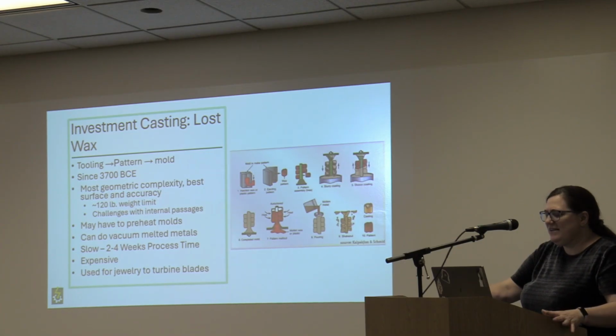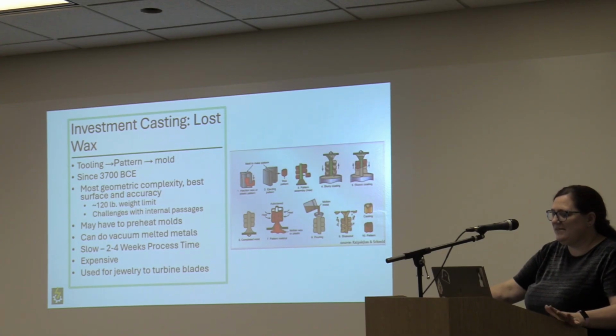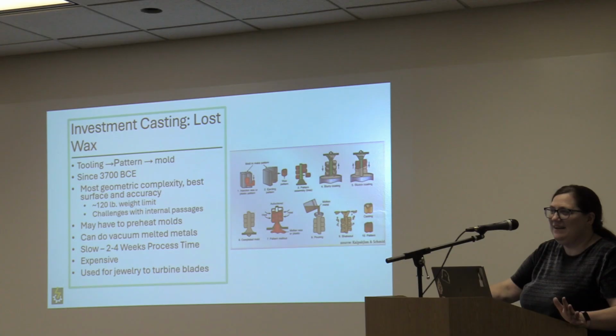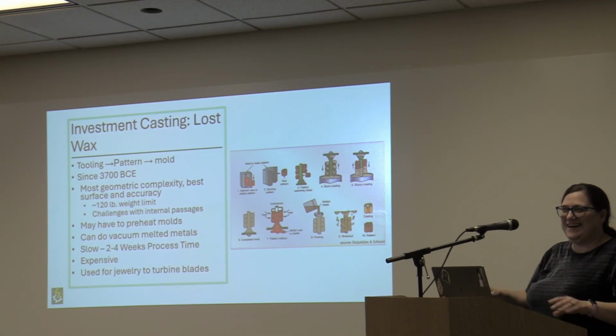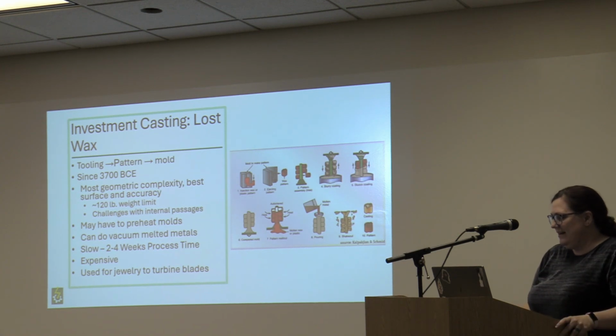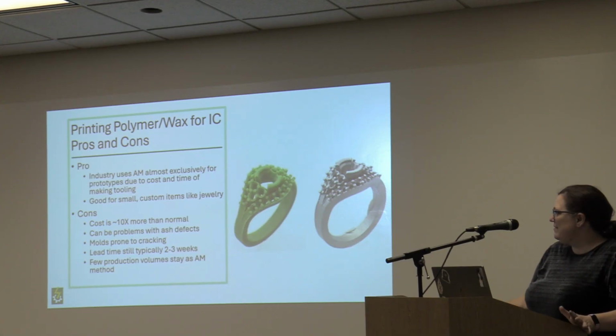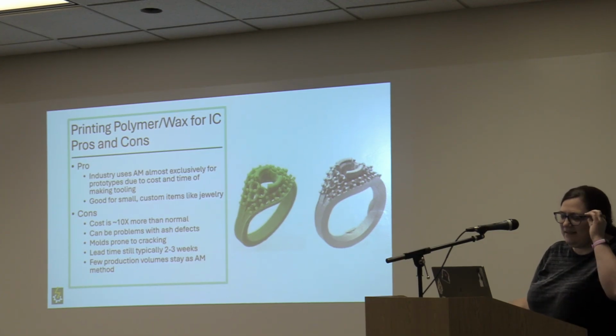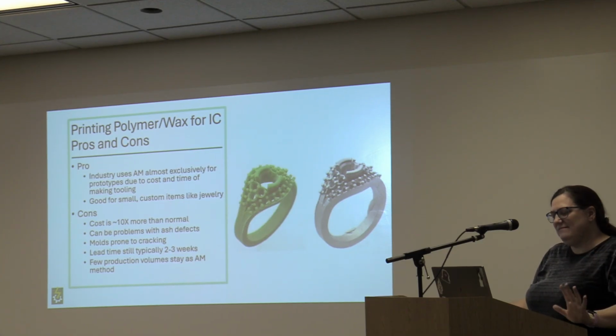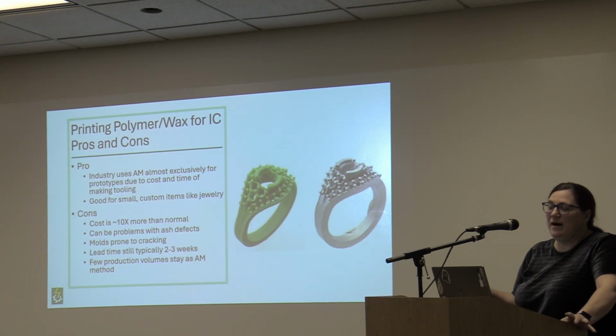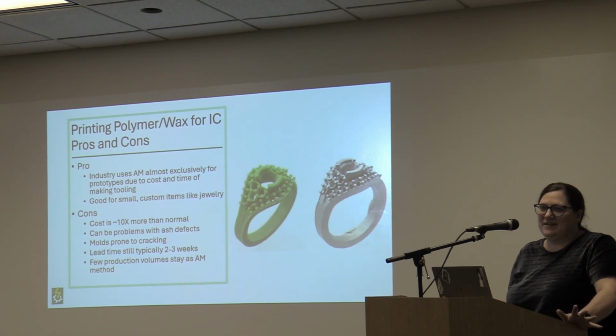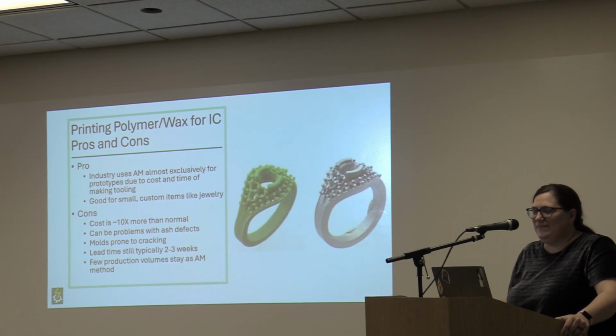And the biggest drawback is that it's a slow process, especially for bigger parts. You're talking 2 to 4 weeks of process time, not queue, not lead time, just how long all these steps take. So if you're using 3D printing, you're typically having very similar process time. You make it a little bit faster, but typically that is an issue. But at this point in time, additive investment casting is pretty much always what is used for prototypes. I've been told that nobody is making tooling anymore in investment casting until the design is locked down. But if it's a prototype, it's going to be done additively.